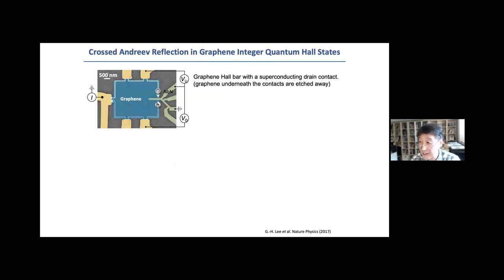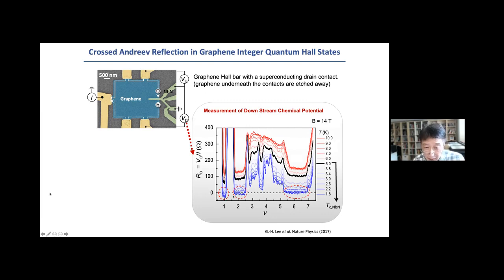Indeed, this experiment was worked out a few years ago already. Here is a graphene and niobium nitride electrode, except now the niobium nitride electrode is so thin, something on the order of 100 nanometers or even less, right? We bias the upper side of the quantum Hall edge and ground with the superconductor, and we monitor the downstream chemical potentials, normalized with the current, and that is what we call the cross-Andreev reflection resistance. Whenever we see that the quantum Hall effect is well developed, like the 6, 2, and 1 in single-layer graphene, we do see that indeed the downstream chemical potential dips into the negative side.